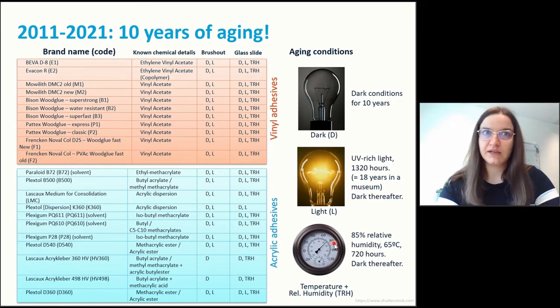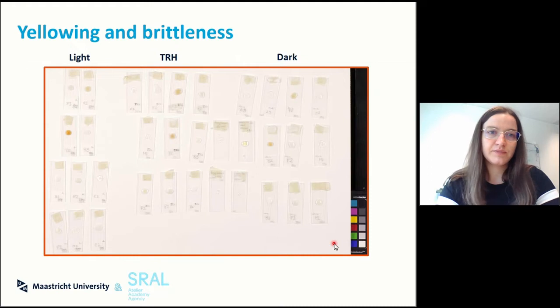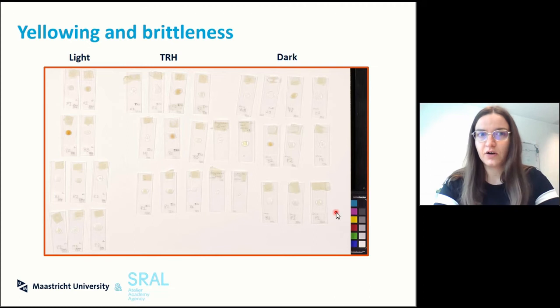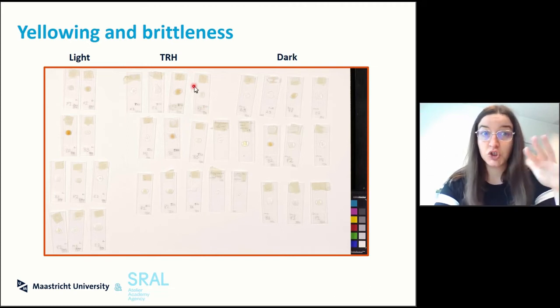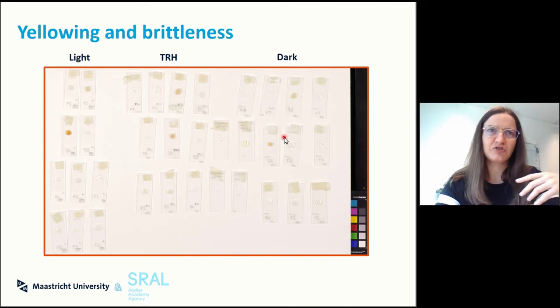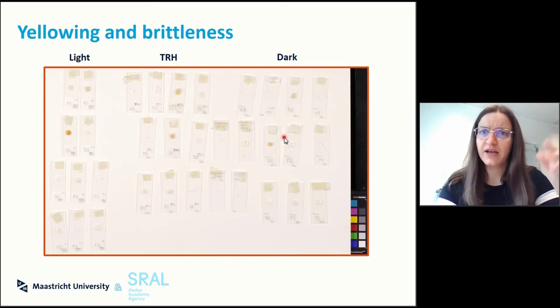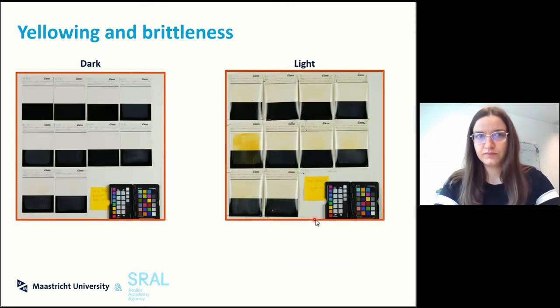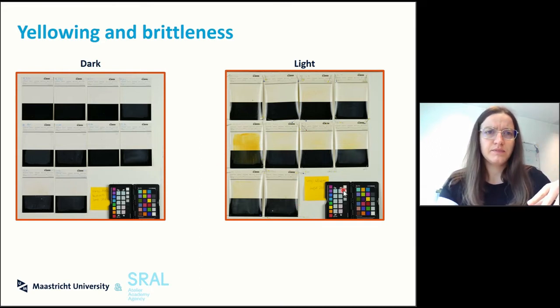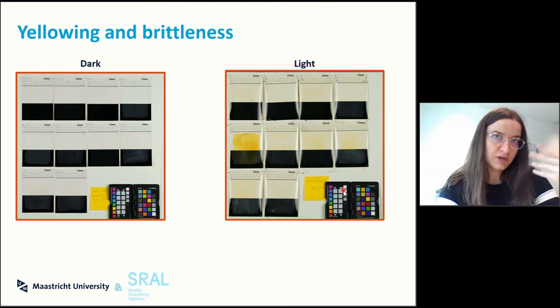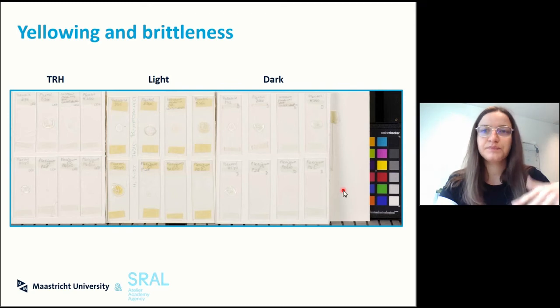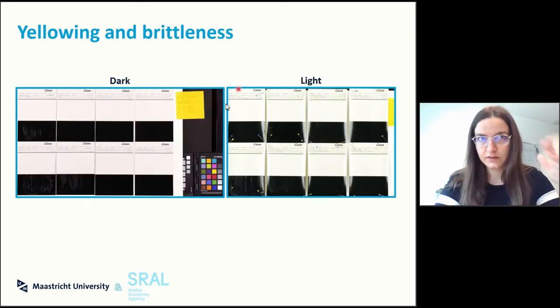So the first evidence that we can get from our adhesives when we recover them 10 years after aging is how do they look. And immediately, by comparing them with the picture of what we created at the beginning, we can see that this is, for instance, a set of slides of vinyl adhesives. Some of them had huge change in colors, some of them started to crack, some of them started to actually get off the slide. Same business can be done with the brush outs, which again in some cases you see an extreme difference. And as it was done for the vinyl adhesive, you can also take pictures of the acrylic adhesives, both on glass and in the brush out.